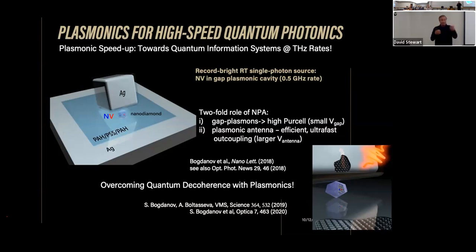And actually, what typical calculations show is the gap should be, let's say, a few nanometers, where the size of this cube should be 50, 60 nanometers. And then you do both. You have very strong Purcell enhancement and very efficient outcoupling before any decoherence happens, or before even loss happens. So you could outcouple the photon before even the plasmons decay, meaning it would be loss-free outcoupling.